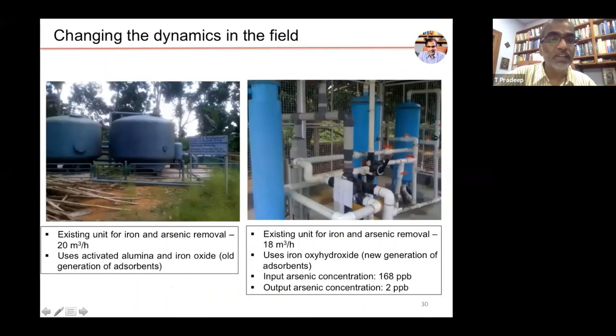And we put it in the field. And traditionally, this is what is there in a field, about 40 cents of land area, typically used for a village water scheme. And you have tanks, which contain typically activated alumina, and they adsorb arsenic, large capacities, large tanks are needed. Now, because of these enormously large capacities, we reduce the land area from 40 cents to less than 5 cents. And the overall construction is just this. As tiny, you will see much smaller thing later on.